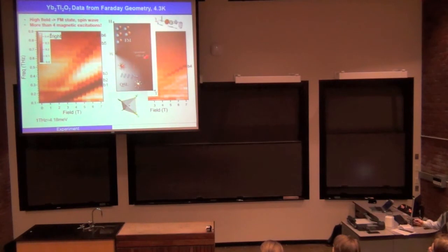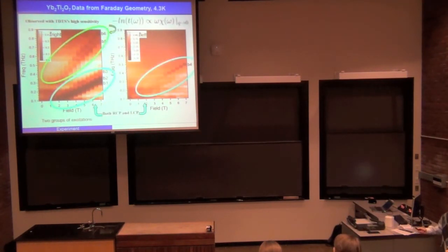So remember, at high field, we would have this polarized state of field-induced long-range order state. So at high field, you would expect this absorption to be of the spin wave nature. But at low field, we are supposed to see these signatures of Dirac strings. And the first feature we realized is that we see two groups of excitations. This group with about the same slope, and the slope in this figure is the same as effective g factor. And also we see another group with a higher effective g factor. And another interesting thing about this spectrum is here we see absorption from both right circular polarized channel as well as left circular polarized channel.